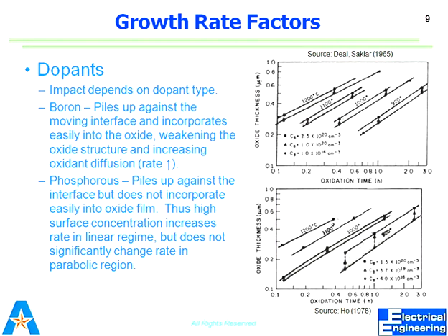crystal has become weakened. Due to the weakness, it has some space for the oxygen or any oxidant, or the water molecule in the case of wet oxidation, to diffuse through it. The same thing: due to the non-bridging oxygen, the crystal becomes weak and it permits the oxidant to diffuse through it very easily. That's why the reaction goes up, because the diffusion becomes easy. So the bottom line is, in this case, diffusion is easier due to the weak crystallographic system.